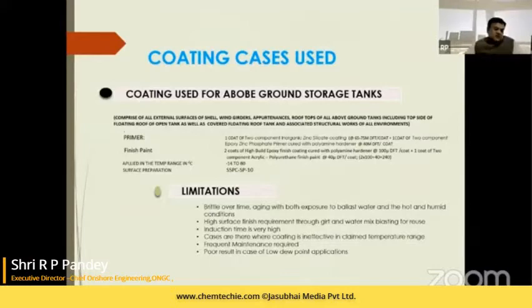So what are the limitations in our systems? The coating becomes brittle over time, aging with exposure to ballast water and hot and humid conditions. It requires a high surface finish through grit and water mix blasting for reuse. Induction time is very high. There are cases where the coating is ineffective in the claimed temperature range. Frequent maintenance is required, and results are poor in low dew point applications.